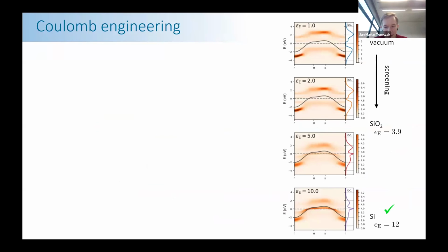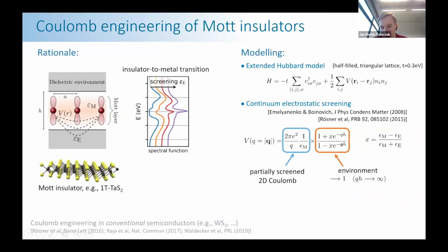That's correct. In this kind of ansatz, this additional screening is largest for small q, which means rather longer range interactions. So you would think, in principle, if you would limit yourself just to local and nearest neighbor, that the more screening would favor the insulator, because typically the non-local part gets screened more effectively than the local part.